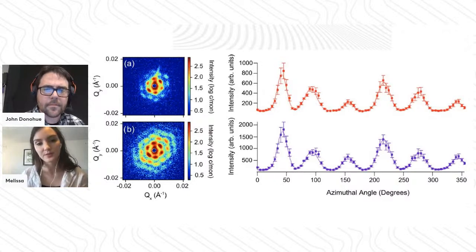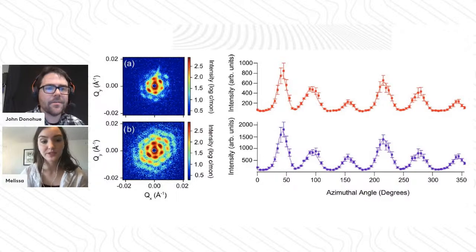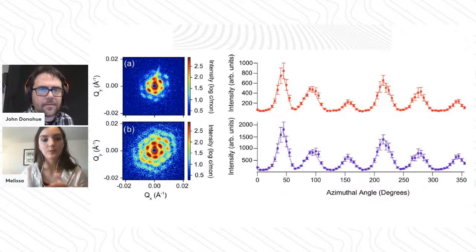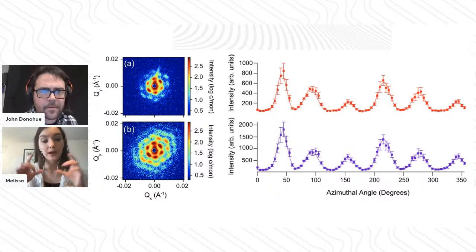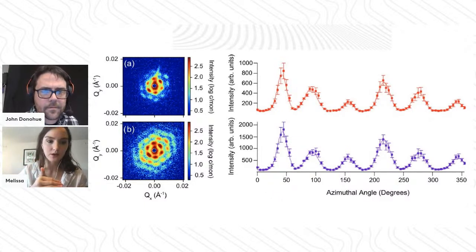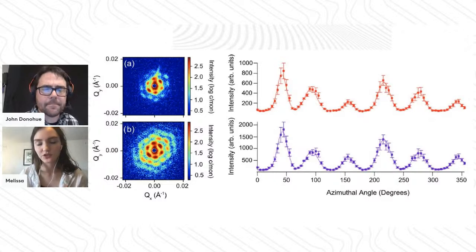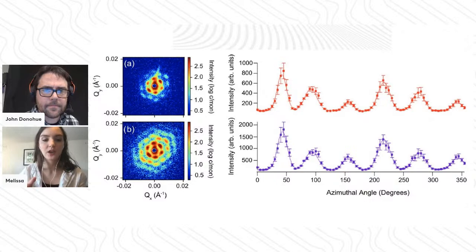In fact, this is not what we see. We see that we're actually able to precipitate some order when we convert from our thermal equilibrium down to our square lattice. We actually end up going from a ring-like to a more square-like pattern. We have simulations which suggest that this is due to a change in topology of the skyrmion tubes, wherein they have to merge and separate in order to reorient into that square pattern.